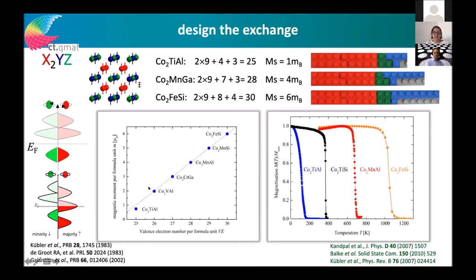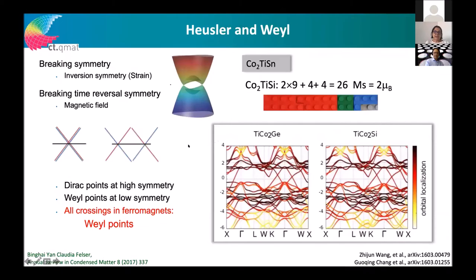For example, the half-metallic Co₂-based Heusler compounds — like Co₂TiAl — have 25 valence electrons: 24 electrons fill the band and one additional electron creates the magnetism. You can make a whole row of such compounds with quite high Curie temperatures, interesting for applications — for example Co₂FeSi has Tc around 1100 K.